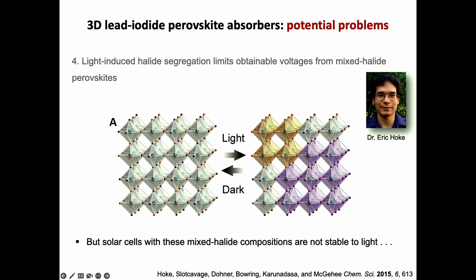The halides segregate to bromide-rich and iodide-rich domains, and the bromide-rich domain has the large band gap. The iodide-rich domain has the small band gap, and all electrons and holes that you generate anywhere in this material want to be in the small band gap material, because that's the lowest energy configuration for those carriers. So that means no matter where I generate my electrons and holes, they are going to funnel here, and I'm going to get the voltage of an iodide perovskite cell.